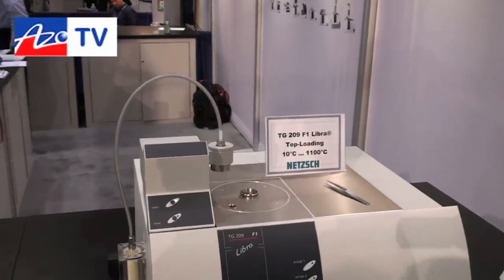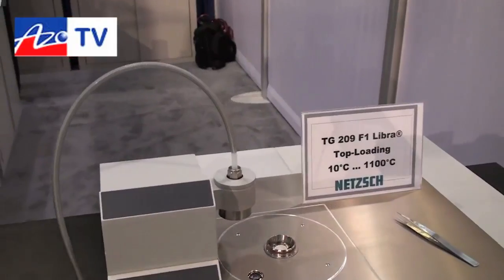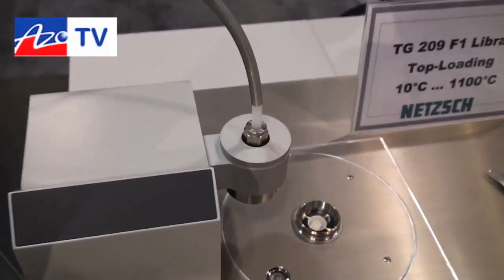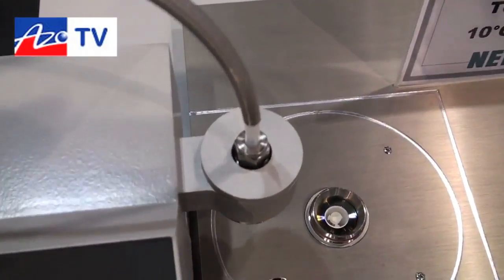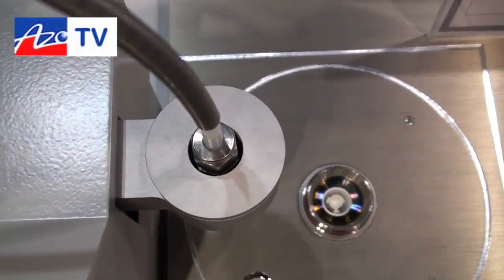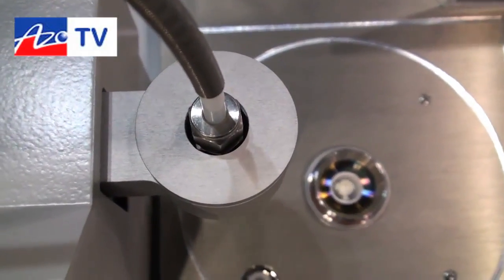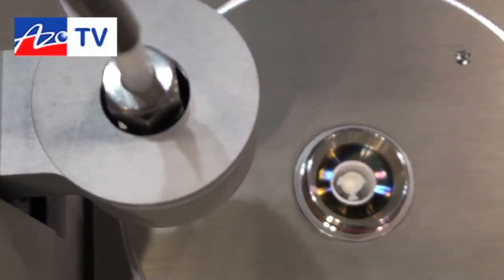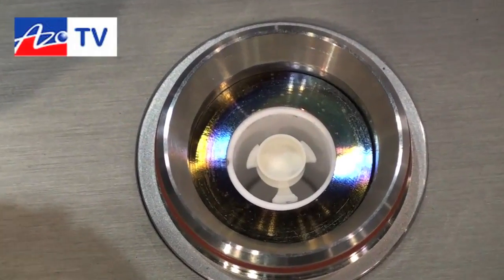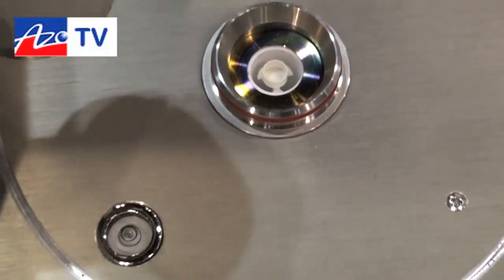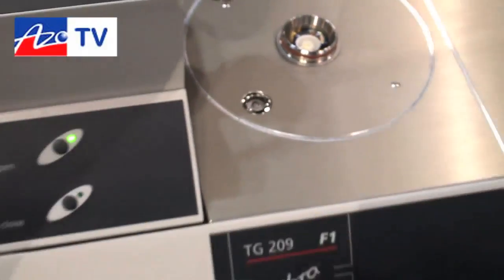Certainly. The furnace is a new ceramic furnace that has the advantage that it can go to 1100 degrees Celsius, which is higher than the normal 1000 degrees C furnace that most TGAs can go to. The ceramic furnace also heats faster, up to 200 K per minute, and it's more corrosion resistant. So in TGA, you're going to be producing a lot of reaction byproducts that come off the sample, and the ceramic furnace will be much more corrosion resistant to any corrosive gases that might be formed.